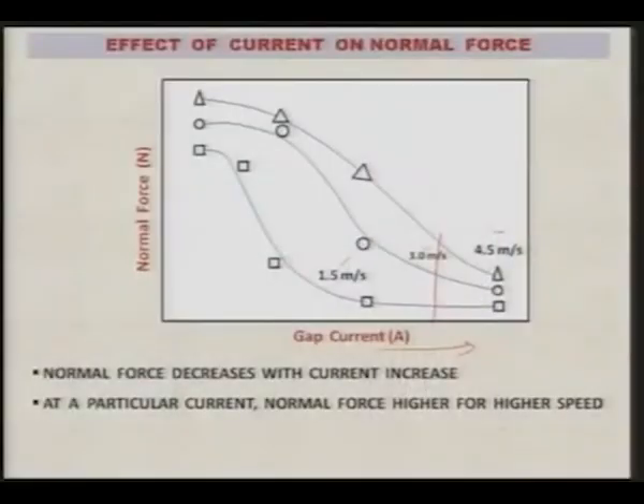So, that is very clear over here. As the gap current increases, the amount of heat input to the workpiece is more, and if the heat input is more, then definitely its temperature will be higher, and with a higher temperature the workpiece will become softer. That is why you can see that as the gap current is increasing, the workpiece becomes more and more soft, and the normal force decreases, as you can see over here at any speed.